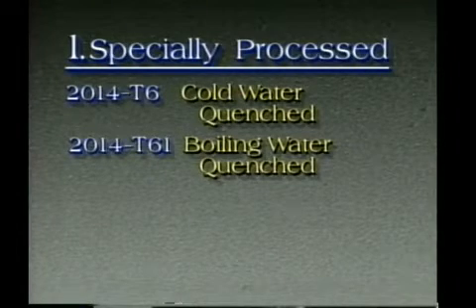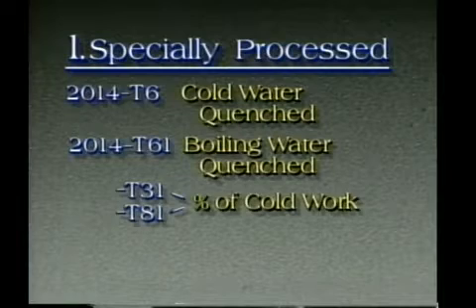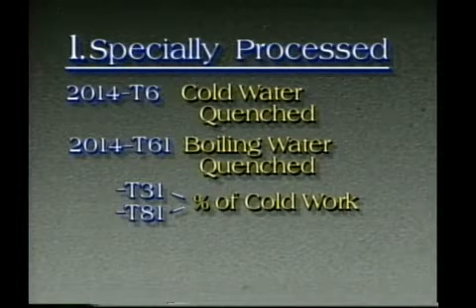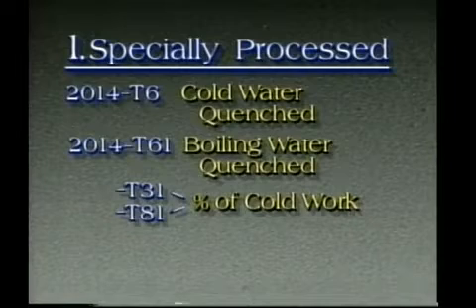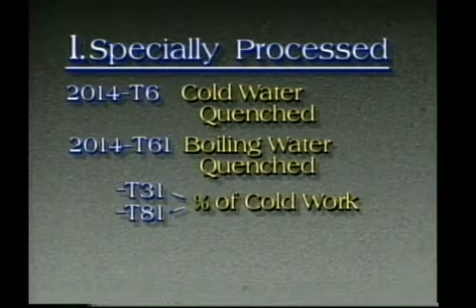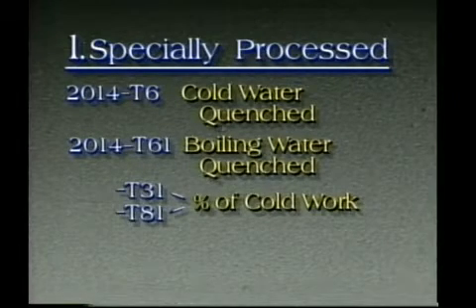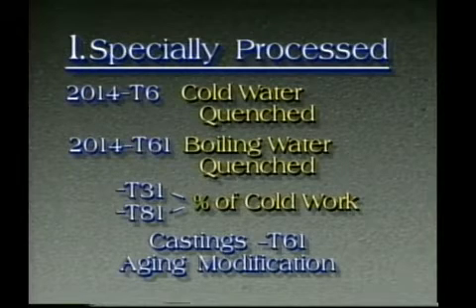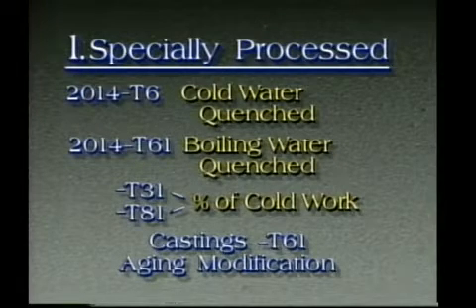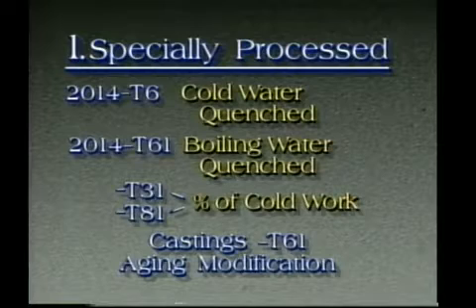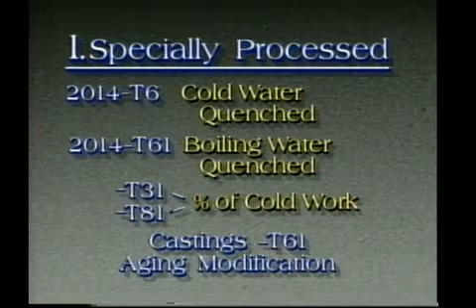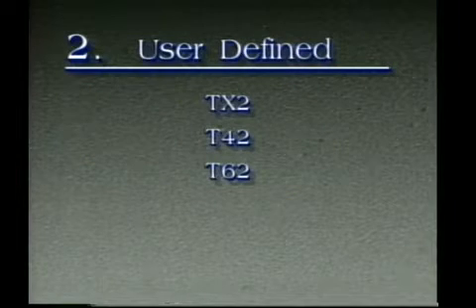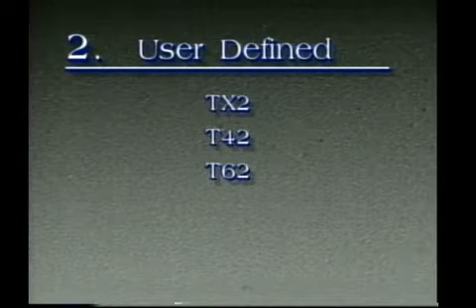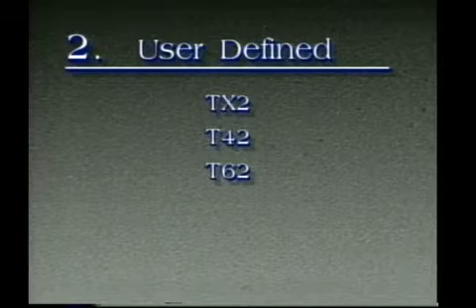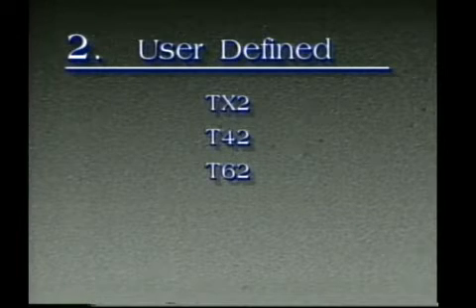When one is used with T3 or T8, as in T31 or T81, it identifies a specific level of cold work, usually 1 1/2 to 3%. For castings which are heat treated and use the T61 designation, it usually refers to an aging modification rather than a quenching or cold work modification. The user-defined descriptor 2 takes the common form of TX2, such as T42 and T62.